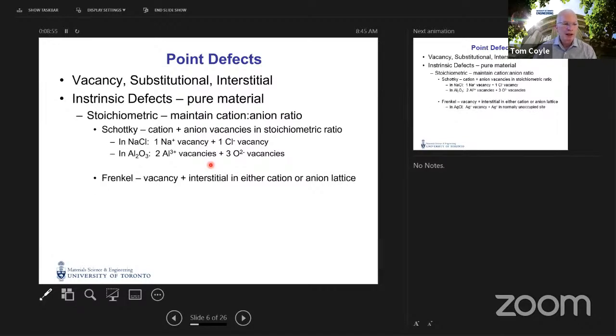Another type of intrinsic stoichiometric defect is known as a Frenkel defect. And this is a combination of a vacancy plus an interstitial. So for example, in silver chloride, to pick another ionic compound, a Frenkel defect would consist of a vacancy on a silver site, with that silver ion having moved into a position in the lattice which would not normally have an atom located at it. And so an interstitial site.